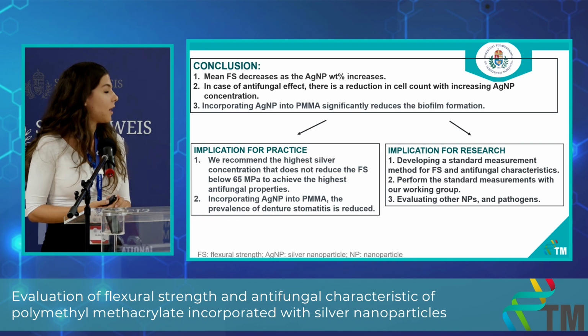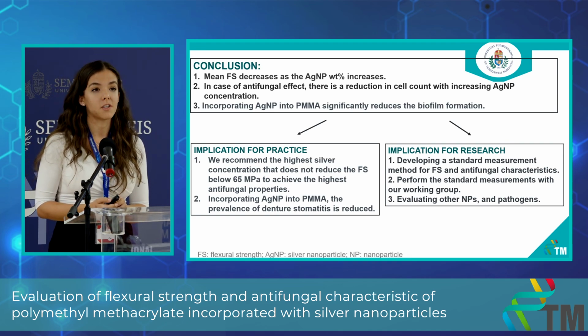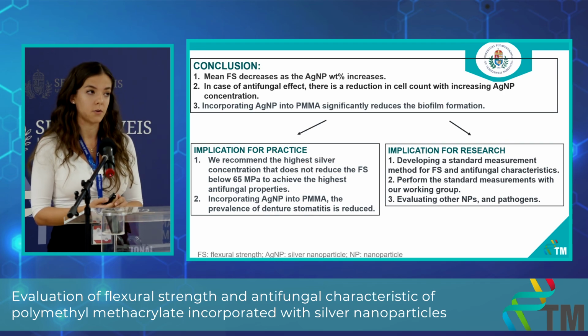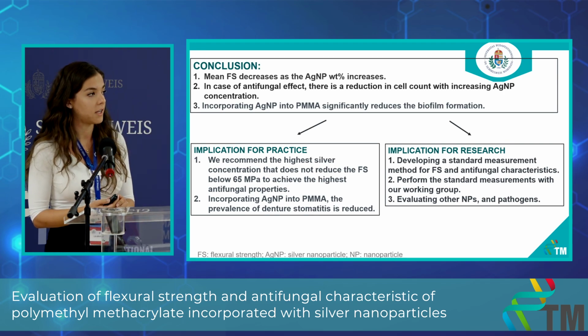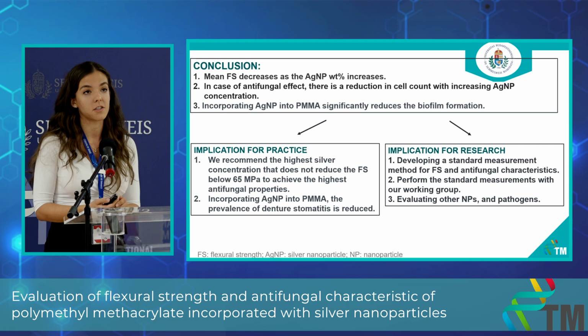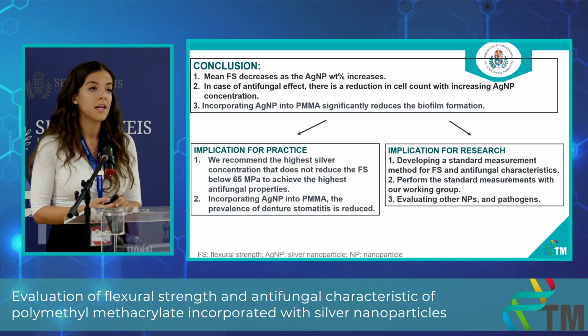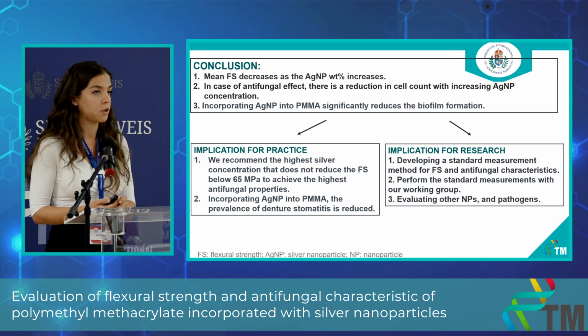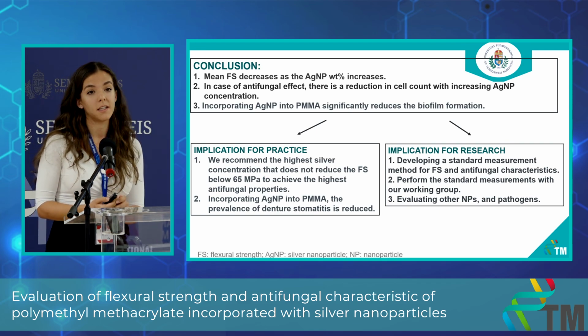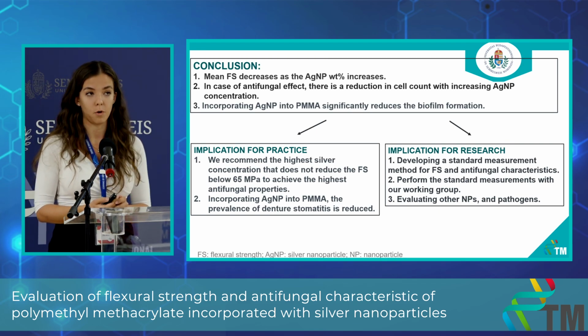And you can see here our main conclusions. The mean flexural strength decreases as the silver nanoparticle concentration increases, and in case of antifungal effect, there is a reduction in cell count with the increasing silver nanoparticle concentration. And incorporating silver nanoparticle into PMMA significantly reduces the biofilm formation.